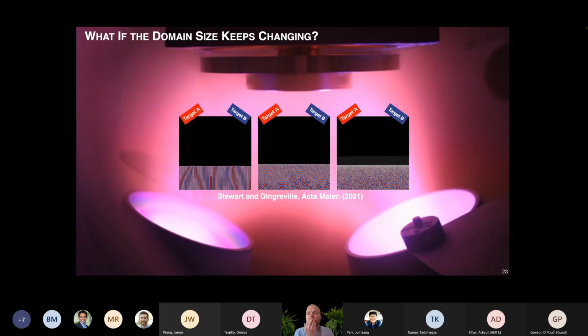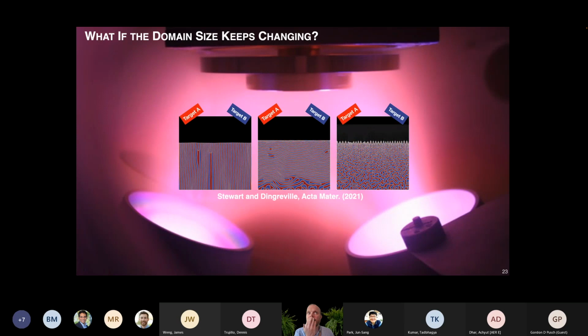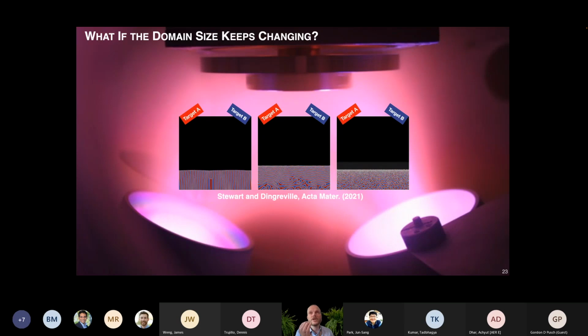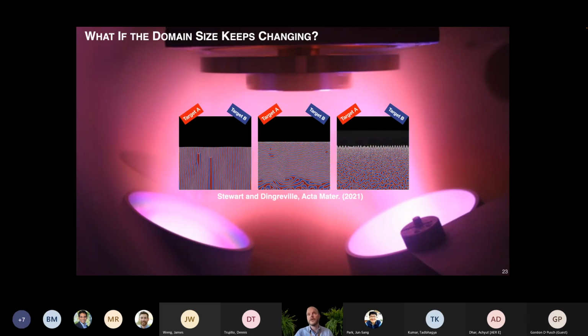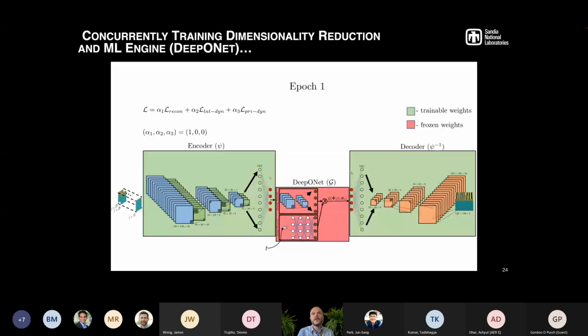Recently, we've been looking at more complicated problems, where the size of your domain changes as a function of time, and the microstructure also changes. In this case, we had to change our architecture slightly. Instead of first training the autoencoder on our training data set and then training the DeepONet, we had to come up with a concurrent training dimensional reduction / ML engine to capture the moving boundary, and at the same time capture the way the microstructure evolution changes.